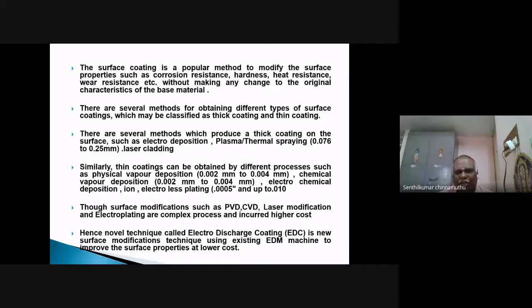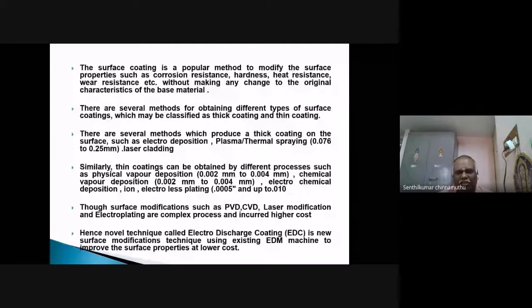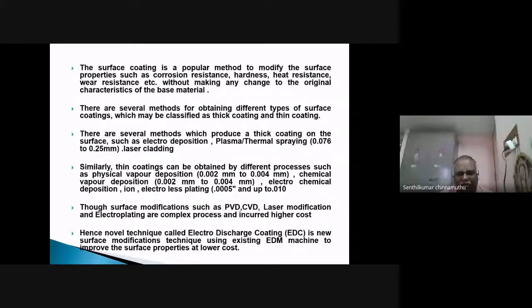Thick coating includes plasma coating, thermal spraying, laser cladding, and electro deposition, with which we obtain 0.076 to 0.25 mm of coating thickness, which is called thick coating. See, the above said coating processes need sophisticated machines, which incur higher cost, and the process is also complicated.